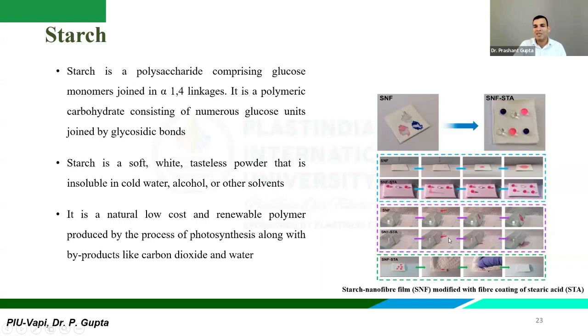So you can see in these images again with changes. Starch nanofiber film will wet the tissue, but when you treat it with stearic acid, it will keep the water in the form of pearls. In the same way, this is talking about the contact angle. And again, in the same way, you would find that in starch stearic acid based material, the tissue doesn't get wet. It remains as it is.